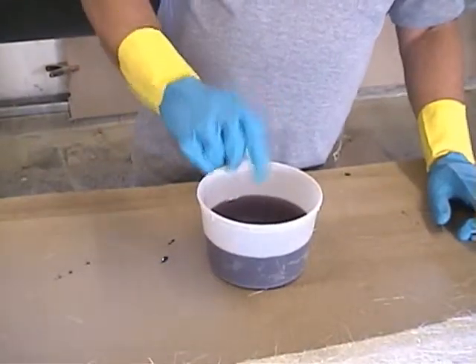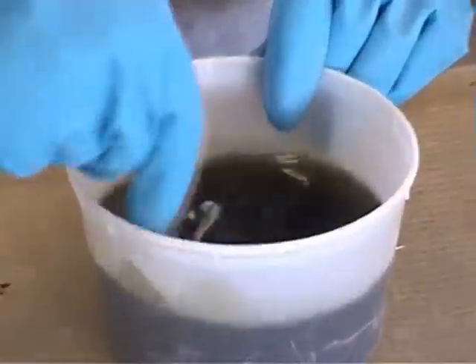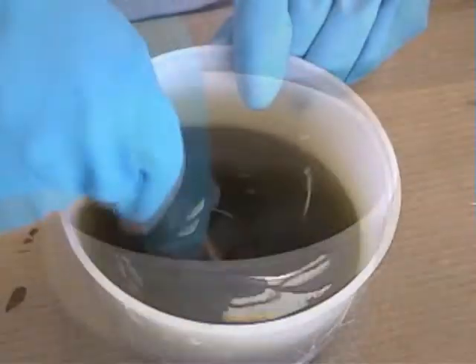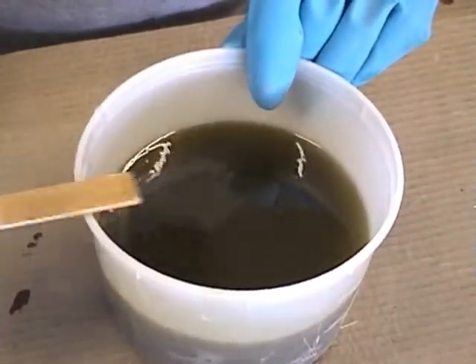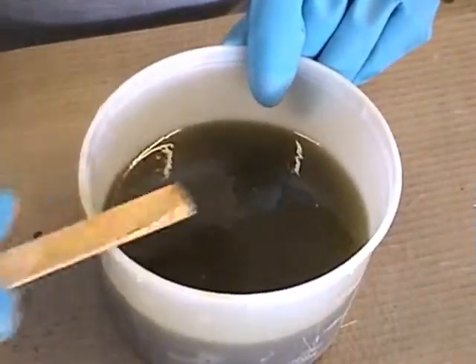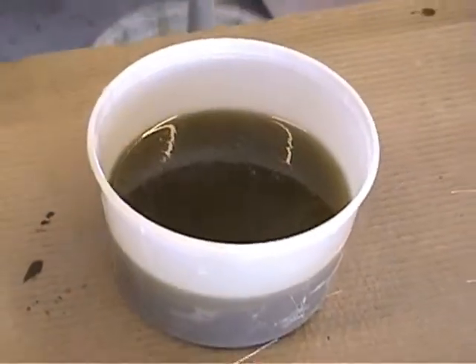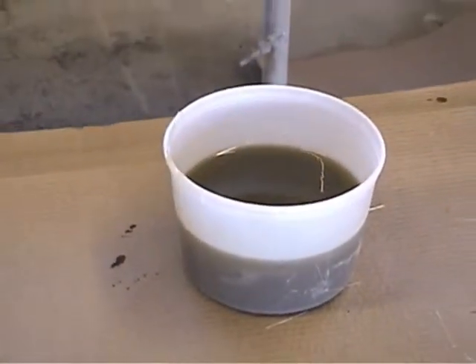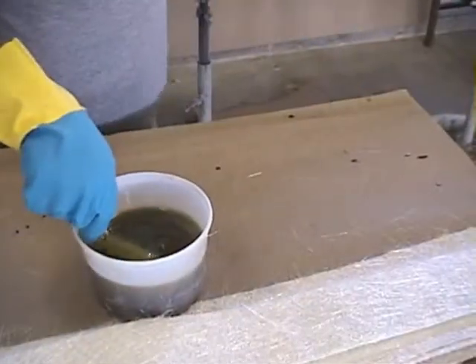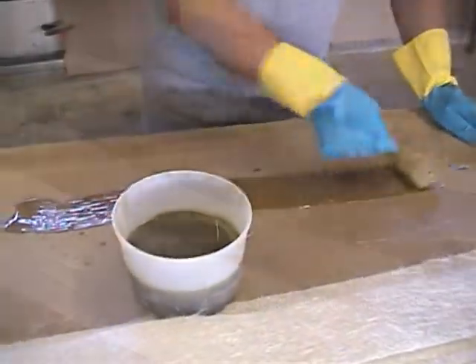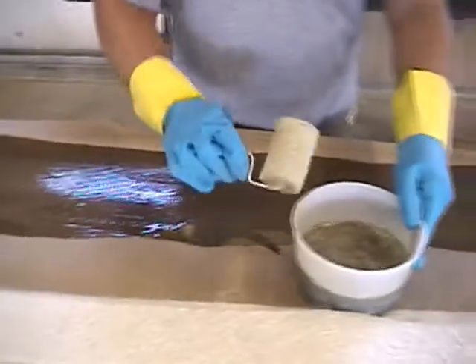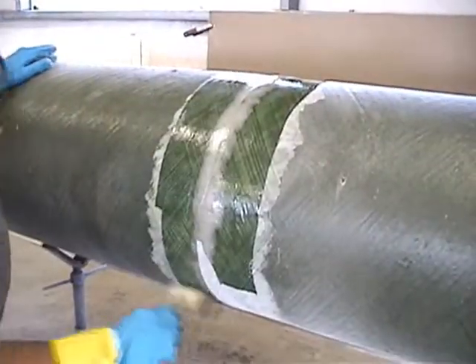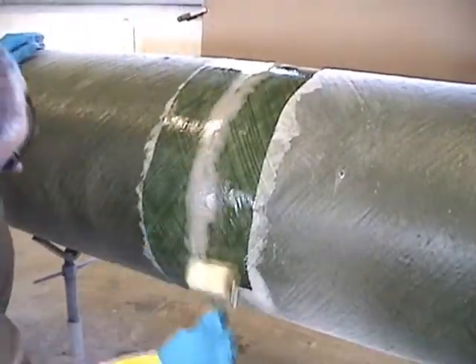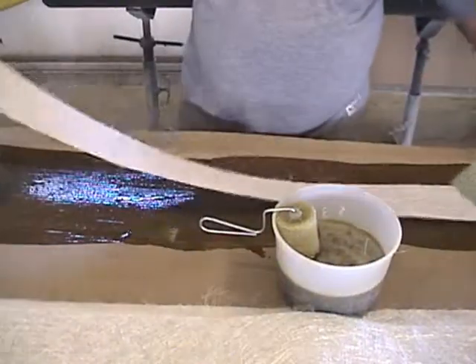Pour it into your resin. Use your stir stick to stir the resin and catalyst very vigorously. You'll notice the resin started out as a purplish color. Now it is turning into a green tint. When you see a lot of small air bubbles starting to form, you'll know you have the catalyzation all the way through the resin. Always wet your rollout surface with mixed resin before you lay out and wet your glass layers. And wet out your part before applying any glass and resin.